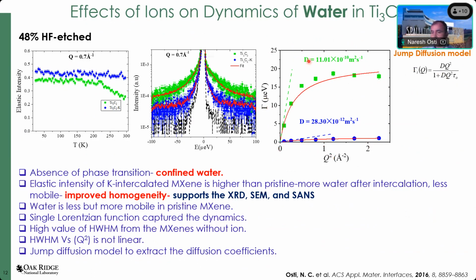Which is 1.01 times 10 to the power minus 9 meters squared per second, which is just half compared to the bulk value. Now, the diffusion coefficient of the water in metal ion intercalated MXene is already 2 orders of magnitude smaller compared to the value that you have obtained for the pristine MXene. It tells us that the water in metal ion intercalated MXene is totally confined in between the layers, but this half decrease in the bulk diffusivity value indicates that the water in pristine MXene is not in between the layers. It might be somewhere in the stack or somewhere in the large voids. That's why we don't see a significant reduction in the water mobility.